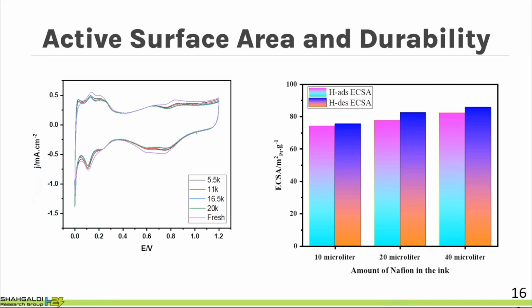Through the half cell, you will end up with a graph like that, the cyclic voltammetry, from which you can calculate the hydrogen adsorption and desorption and calculate the surface area. The surface area comes from platinum here. But then you can do the BET in order to get the surface area of your carbon-based material as well.